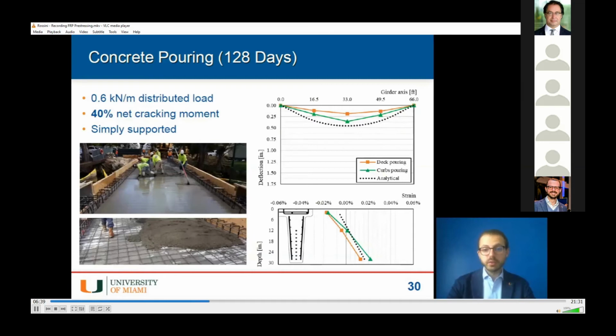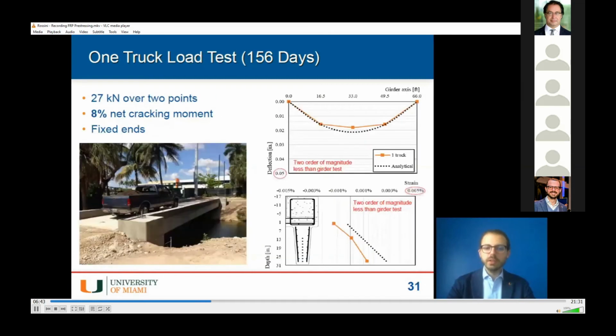Finally, when the structure was completed, we brought the truck on site. We load tested the final structure. And also in this case, even though we are at a lower order of magnitude because now the structure is much more stiff, we have very good agreement with our theoretical expectation.